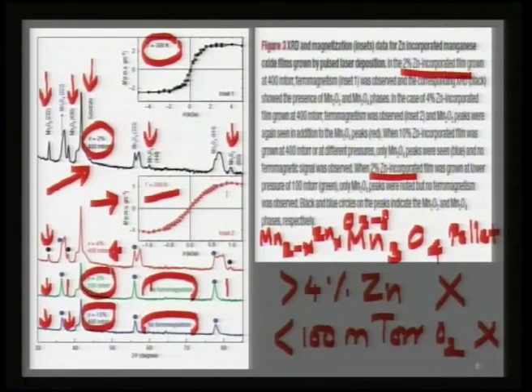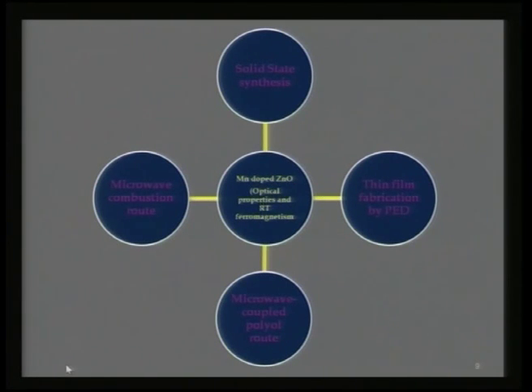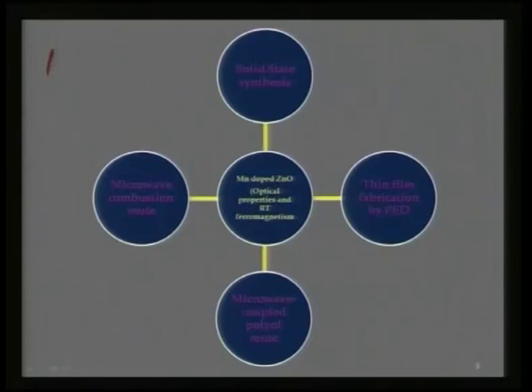This group went on to propose that it is not manganese doped into ZnO — rather it is a defect-induced concentration in Mn2-xZnxO3-δ which is actually stabilizing a ferromagnetic signal above room temperature. This is a very classic example showing that characterization techniques can be both useful and risky: blindly looking at a magnetic signature cannot substantiate that it is a true property of a material. Especially when doping impurities of the order of 2–4%, one must be extremely careful to see what is the exact mechanism underlying the magnetic property.